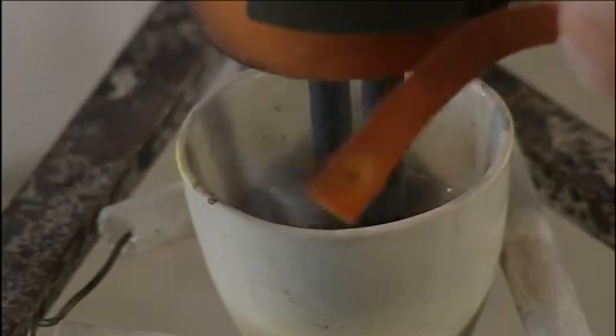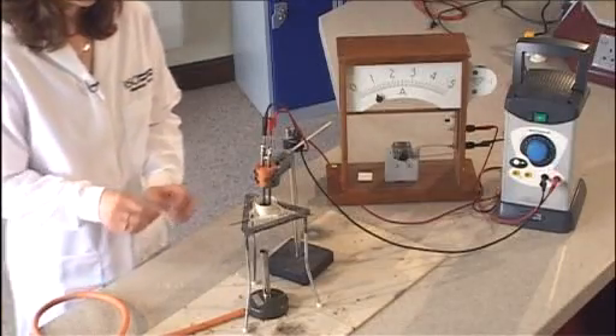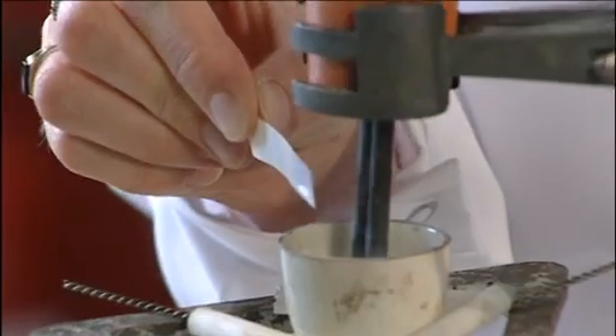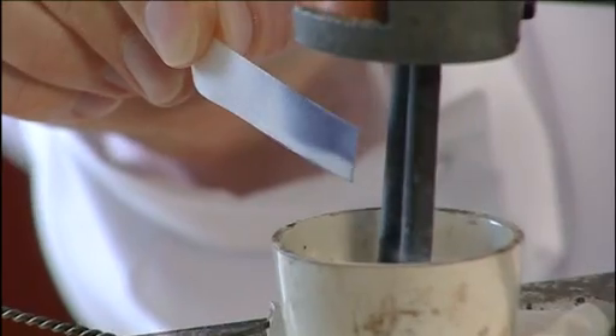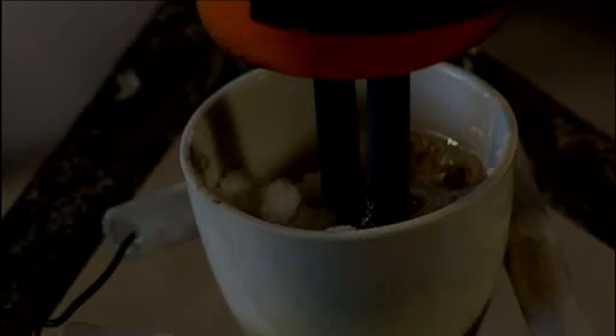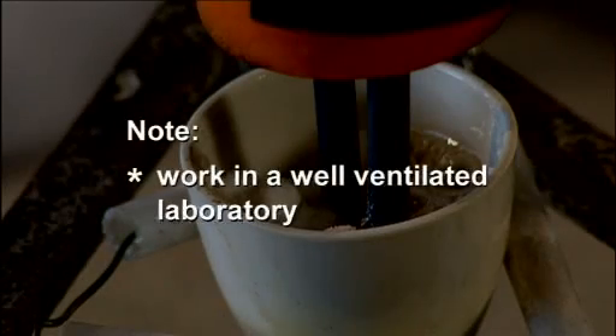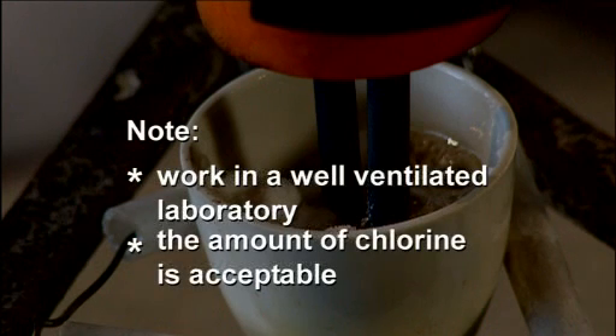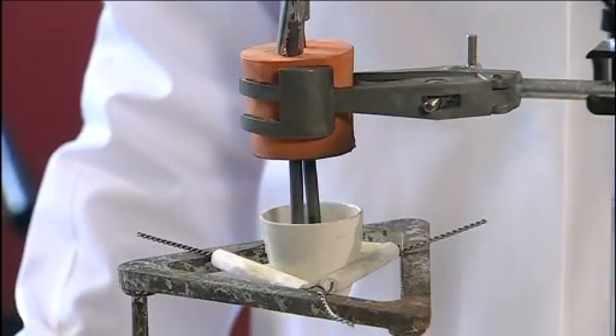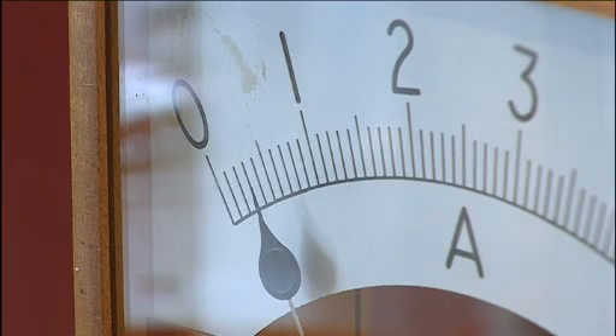An alternative test is moist starch potassium iodide paper, which you can see clearly goes black. The electrolysis may be carried out in a well-ventilated open laboratory. The amount of chlorine generated in 15 minutes of electrolysis is small enough to be acceptable in an average-sized, well-ventilated lab. Electrolyse the molten salt for about 15 minutes, adjusting the current to about half an amp.